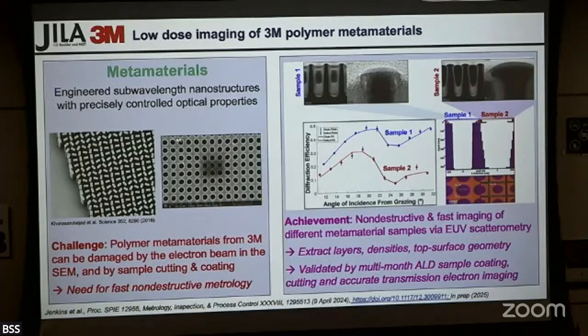So this is scatterometry. We are doing averaging, because this is very fast. We can do this measurement in 10 minutes. So all it is, is the diffraction efficiency from this 2D grating as a function of angle. And just showed that they gave us two different samples. They wanted to see if we could distinguish them.